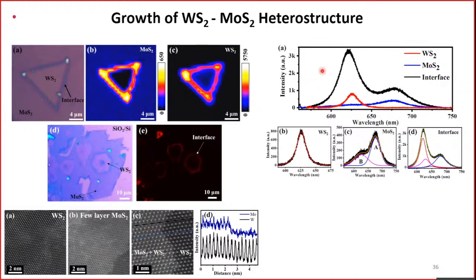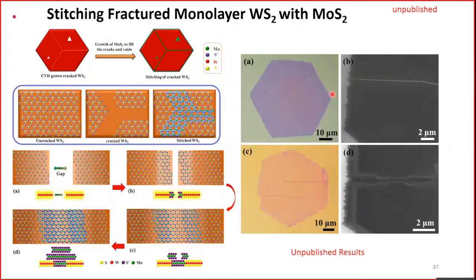So when we make the heterostructure, we see a lot of excitonic emission at the interface compared to the MoS2 and WS2 regions. Again, justifying why heterostructures, right? We call it defect bound exciton and so on. Whenever we have a heterostructure, at the interface there is a possibility that the exciton can be localized.